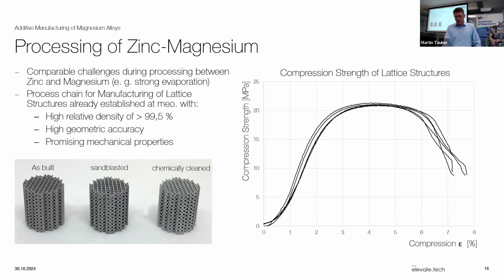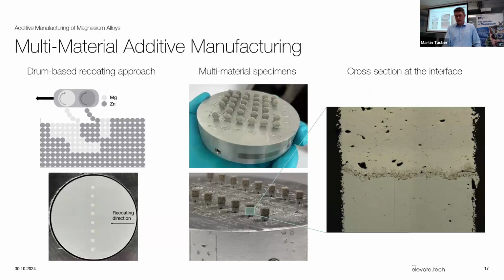And the last outlook that we have is we are really on the research part of this additive manufacturing of new materials, because in a project that we're doing, we're not doing magnesium or zinc, but we have a powder coating system, which is capable of having magnesium and zinc in different containers, and then partially placing the different powder particles within the powder layer. So we're able to print 3D printed parts with different materials in one part. So we can tailor the material in a way that we want it to.